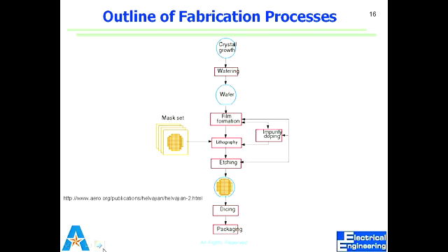Are the wafers single crystalline? Yeah, that's the whole idea. So we get that wafer, which is a plate, 500 micron thick. The thickness and the size all come custom made. Generally, a 4-inch wafer we get for $20 a piece is 500 micron thick. To give a perspective, how big is 500 micron? Half a millimeter? Half a millimeter.